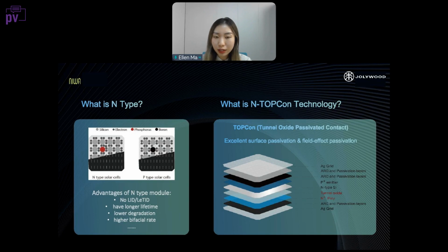Right now, the theoretical efficiency for TOPCon is more than 28.7%, which is the highest theoretical efficiency compared with the HJT. And Jolywood Solar has successfully upgraded the production line from N-PERC to N-TOPCon since 2019. The reason why we chose this technology at its very early stage is because we believe that this technology will bring customers a higher efficiency, and also due to the structure being very similar to the N-PERC, the cost will be much cheaper than the HJT.